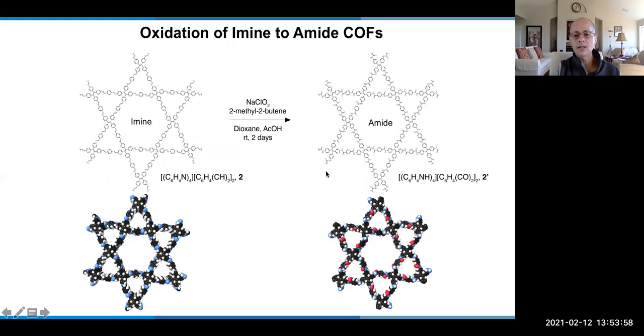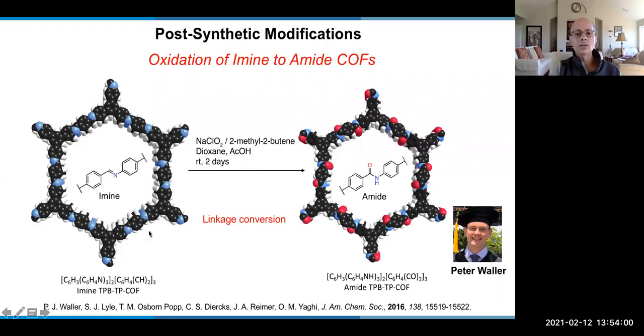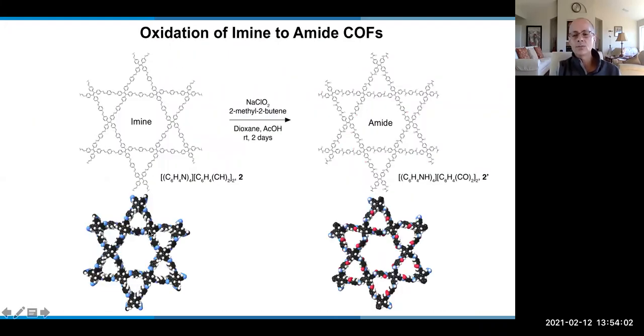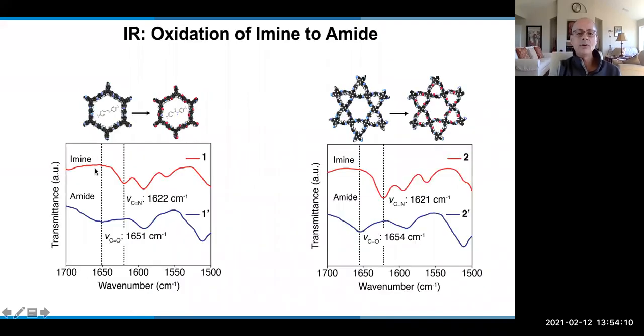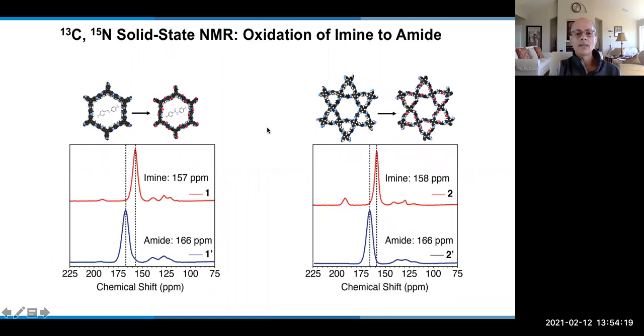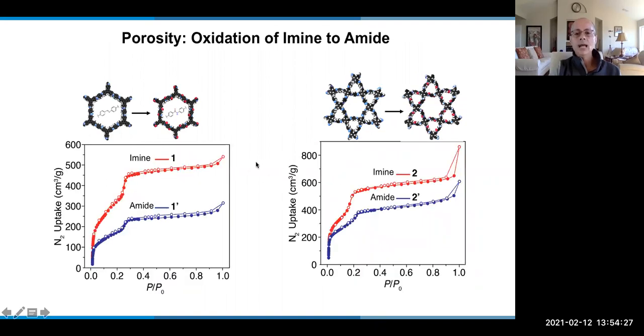And I'll show you the X-ray powder diffractions, but we've done that on the hexagonal structure. And to show that it's more general than just one structure, we showed that in fact, you can do it also on the Kagome type structure. And as I said before, we use IR to show the disappearance, let's say, of the imine and the appearance of the amide in both structures. We use NMR to show the disappearance of the imine and the appearance of the amide, same in both structures.